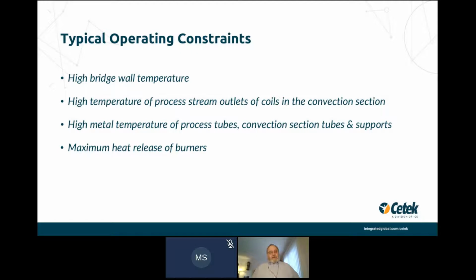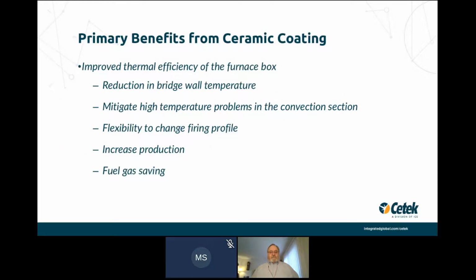So the typical operating constraints that the coatings can address are high bridge wall temperatures, and high temperatures in the convection section, which put strain on the coils there, especially the fins, and also the support structure in the convection section. Also, if you've maxed out on your burners, the coatings will allow you to cut back on the burners a little bit or use a little bit more space there. So primary benefits: improved thermal efficiency, reduction in bridge wall temperature. We mitigate high temperature problems in the convection section. There's a flexibility to change the firing profile by manipulating the heat flux inside the unit, and we can increase production or save energy, save fuel.